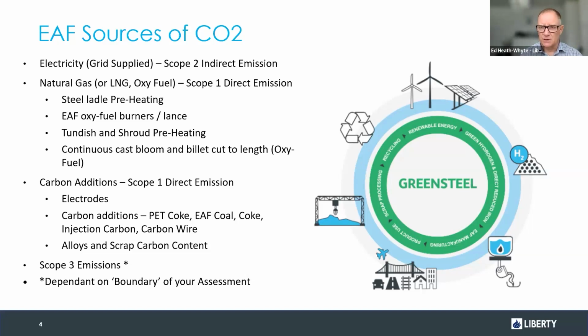And then we have some actual carbon additions, so the electrodes that are used to transfer the electricity for the melting. We make carbon additions of coke, coal, injection carbon and carbon wire, and also within the alloys that we use, ferrochromes, ferromanganese, all of those alloys have carbon within them as well. So within the mass balance of the steel making, we retain some of the carbon in the steel, but we also emit the CO2 from the process.